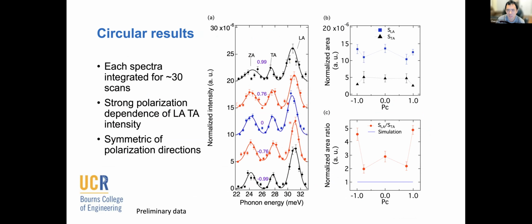But we definitely see a change of the intensity ratio. That ratio change is almost a factor of 2 difference between the circularly polarized beam and the linearly polarized beam. The middle line is similar to what we've done previously, but once we use a left-hand or right-hand circularly polarized beam, the intensity difference is very, very different.